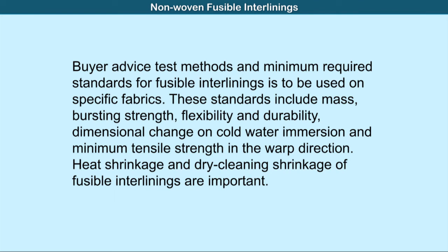Non-woven fusible interlinings. Basically, buyer advice, test methods, and minimum required standards for fusible interlinings to be used on specific fabrics. These standards include mass, bursting strength, flexibility and durability, and dimensional change on cold water immersion, and also minimum tensile strength in the warp direction. Heat shrinkage and dry cleaning shrinkage of fusible interlinings are considered important.